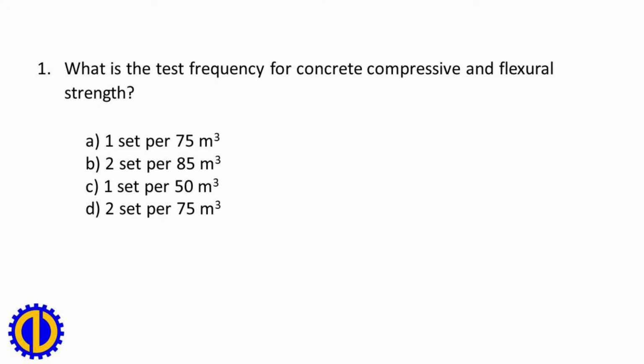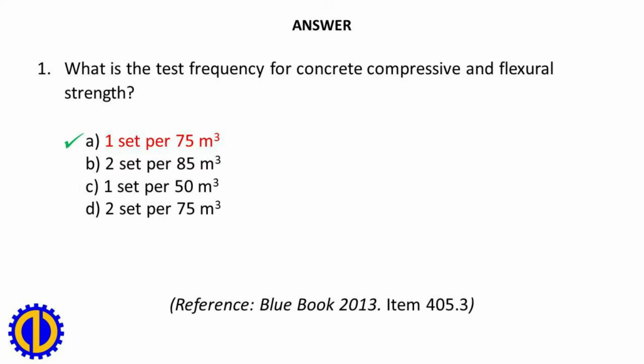1. What is the test frequency for concrete compressive and flexural strength? A. 1 set per 75 cubic meters. B. 2 sets per 85 cubic meters. C. 1 set per 50 cubic meters. D. 2 sets per 75 cubic meters. A. 1 set per 75 cubic meters. Reference, Blue Book 2013, Item 405.3.